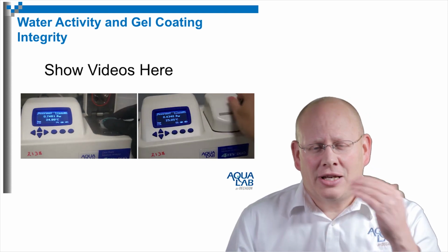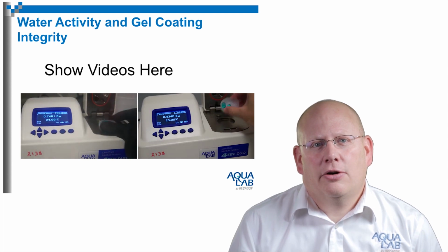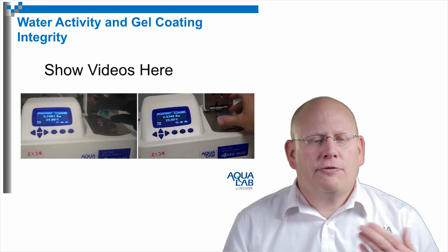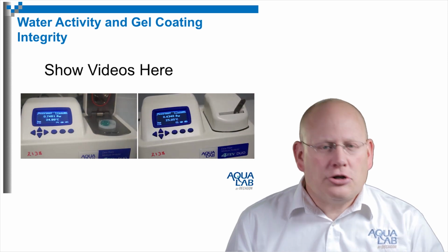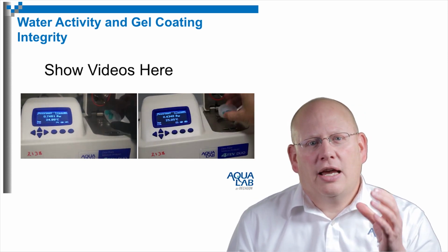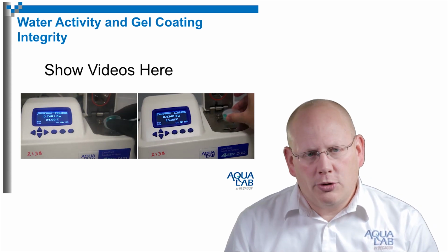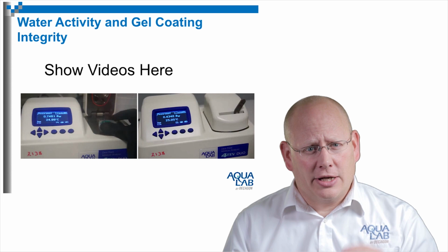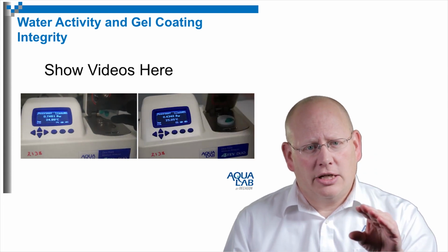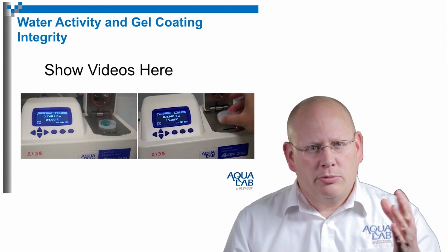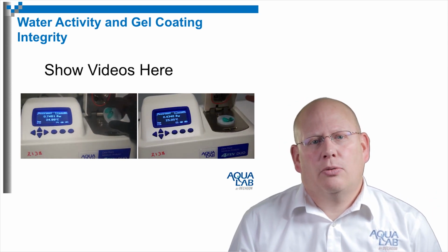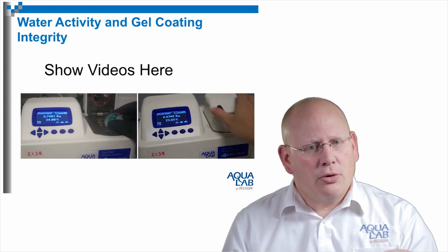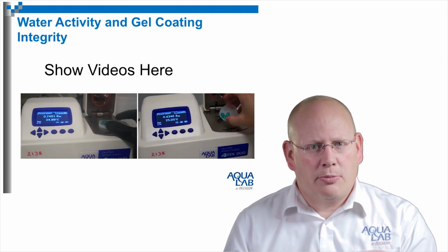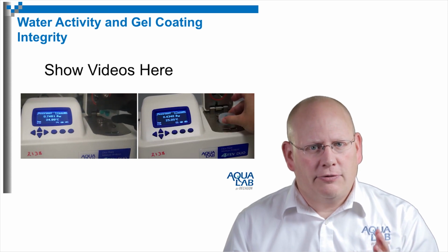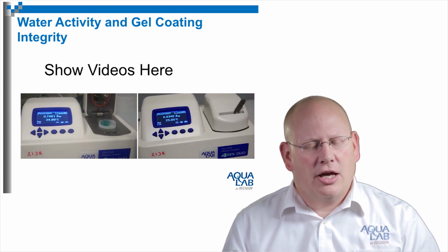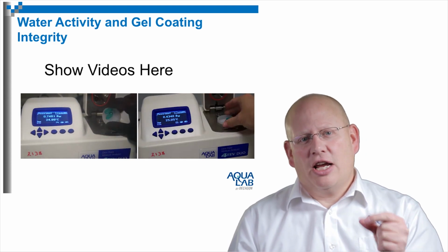water activities. And so you can see here there's a couple of videos that are very interesting to look at. The first video will show the nature of liquid gel caps when they are at essentially room humidity. So you can see as this video progresses what the water activity is on the screen of that product. It's at about room humidity, 34% relative humidity, so 0.34 water activity. Notice as the cup was shaken, those pills remained free-flowing. They weren't sticking together. They were loose and able to shake and move.